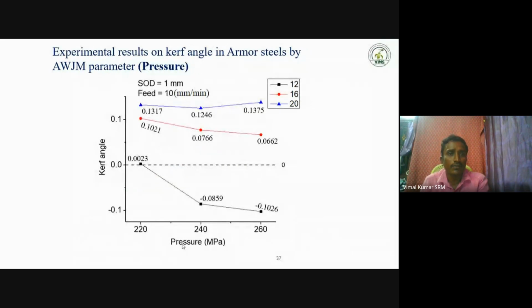Next, the experimental results of kerf angle in armor steel by pressure. Here, we fix the SOD and feed rate for the three plate thicknesses, and we change the pressure. If the pressure value changes, the kerf angle changes at the same time, which means pressure also influences the cut surface of the three plate thicknesses. Here also, the black line is the 12 mm plate, red is the 16 mm plate, and blue is the 20 mm thickness plate. We fix the SOD and feed and change the pressure. Does the kerf angle change or not? Absolutely. If pressure changes, the kerf angle also changes. So not only traverse feed, pressure also influences the kerf angle on the cut surface in the water jet machining process.